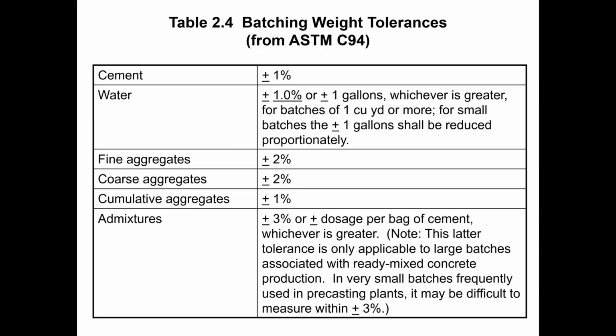For fine aggregates, it's plus or minus 2%. Coarse aggregates, it's plus or minus 2%. But cumulative aggregates, it's plus or minus 1%. And so sometimes people look at that and they think, oh, that's backwards. That it's 1% on each aggregate, but you get 2% on the total. No, what's shown there in the table is correct. You have a more liberal tolerance on individual aggregates than you do on the cumulative aggregates. So for individual aggregates, you have that 2% allowable variation. But for all of your aggregates combined, that total weight should be within plus or minus 1% of the target weight.